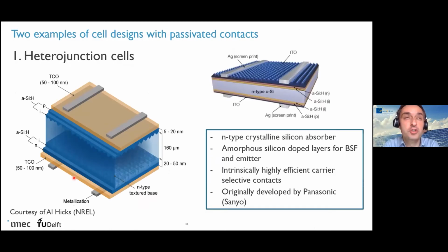So the next step for these N-type wafers to reach higher efficiencies will be using so-called passivated contacts. With passivated contacts, we mean we still need metal contacts, of course, but the metal should never, not even a few percent of the surface area, be in direct contact with the silicon. There are two main types of passivated contact devices being considered, investigated, and even already produced by a few companies.